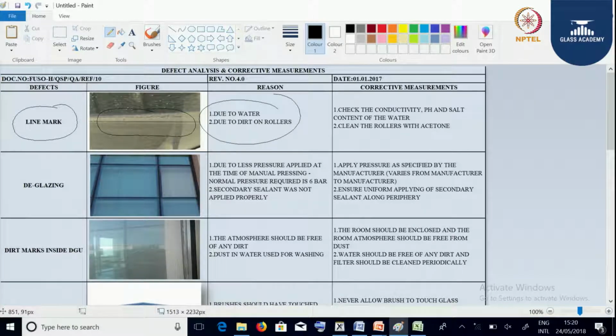We can overcome this issue by checking the water parameters like conductivity, pH and salt contents in the water, and cleaning the rollers with acetone on a regular basis.